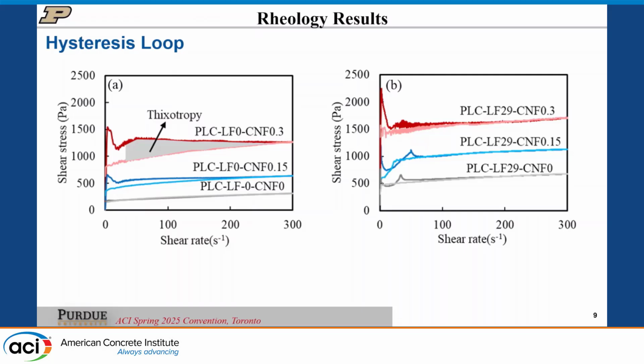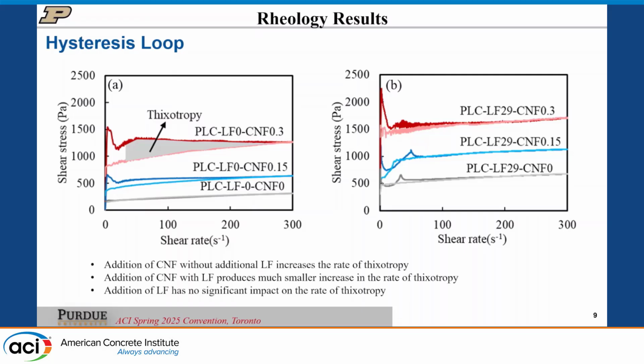When we add the limestone, we see that the effect of CNF on the PLC limestone mixes is actually diminished - we're seeing less increase in rate of structuration with the CNF. And if you compare the two gray lines between the two figures, comparing the PLC system to the PLC with limestone, we also do not see significant effect of adding the limestone filler to structuration.